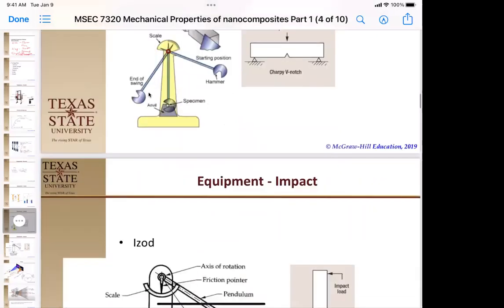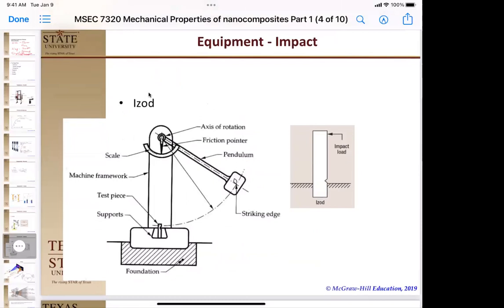All right, so that brings us to the more common one for polymers, the Izod. It's a very similar setup, but notice that the support is down here and we only support one side of the polymer. The notch is also in the opposite direction. Instead of hitting it where it's supported on two sides and trying to fracture it from the backside through the notch, you're hitting it way up here, giving it a torsional component, and you're trying to make sure it starts at the notch and breaks from that. So you're inducing the load and the defect on the actual impact side.